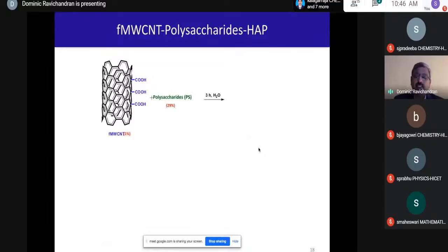And coming on to the composite formation, in the case of the functionalized multi-walled carbon nanotubes, the nanotubes can be attached to polysaccharides or any material for that matter, which can be connected to this carboxylic acid. Our interest was in polysaccharides to be added. So we have used polysaccharides with these functionalized multi-walled carbon nanotubes.